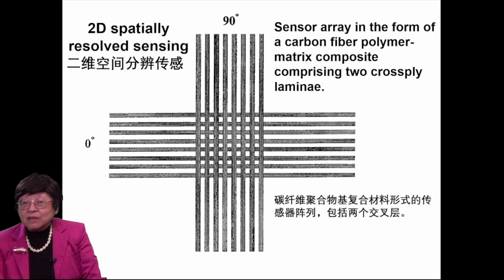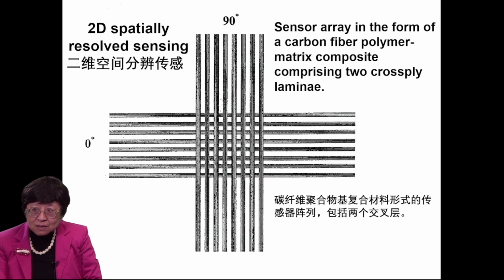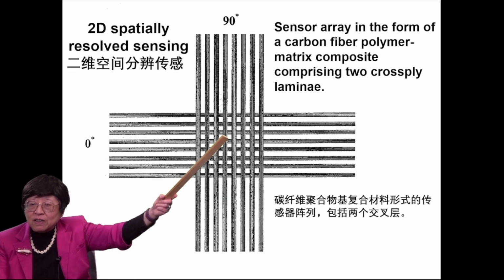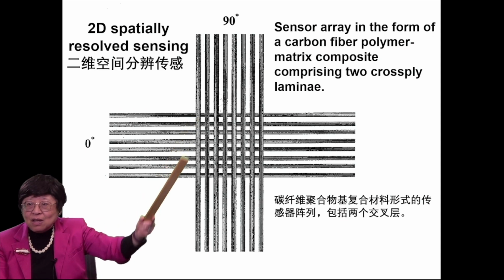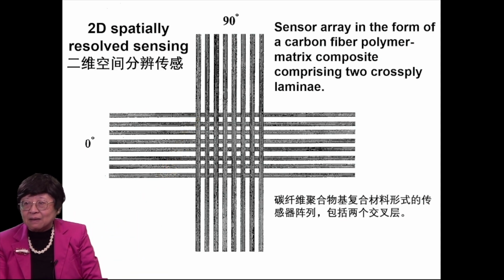Now, this method is also valuable for allowing 2D spatially resolved sensing, because each overlap region is a sensor. So we have a sensor array in the form of a carbon fiber polymer matrix composite comprising, in this illustration, two cross-ply laminae.